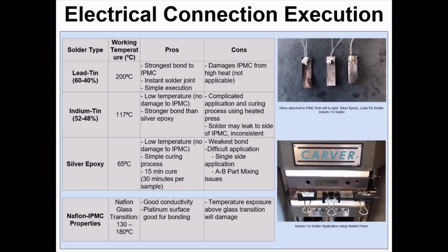So, first we had to attach the wires. Our first way to do this was lead tin solder, which is the typical solder; if you go to Lowe's or anywhere, they're going to have lead tin solder. And this was awesome. It was really strong, really quick, and really easy, but it damaged the IPMC. You can see this is the lead tin solder. The reason it damages it is that it has to stay out of the glass transition temperature range of 130 Celsius, and 200 is way too high for that.